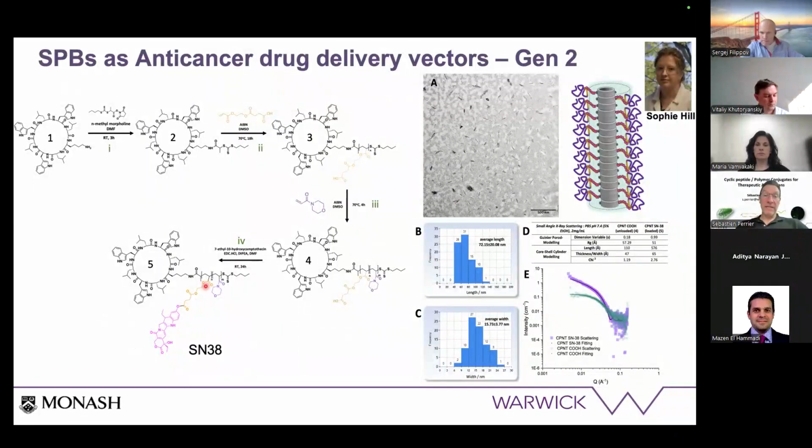The other aspect here is through the chemistry. So I won't insist too much on the chemistry here, but you can see that we're basically growing a polymer away from the peptide. But we're attaching the drug through an ester bond here. And the idea is that the drug in this case is SN38. It's a really hydrophobic drug. So we're doing two things with one reaction. We're creating this hydrophobic inner shell, thanks to SN38 being hydrophobic, and we're also functionalizing with the drug.